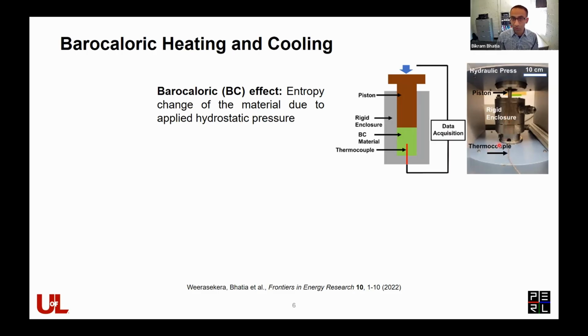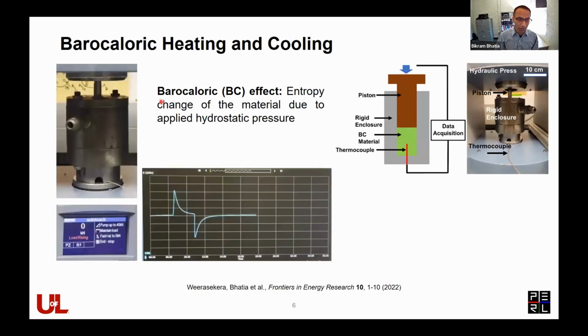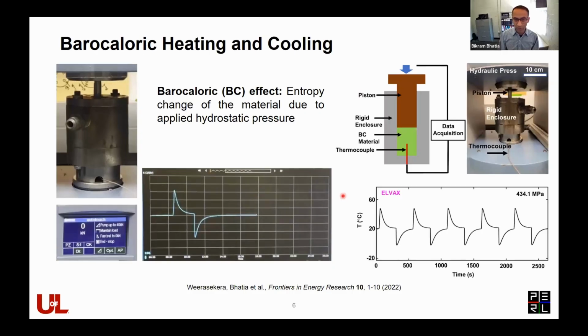And so you can characterize this barocaloric effect by applying hydrostatic pressure. So we do so in our lab using this stress rig that is shown here, which is essentially a piston cylinder system. You fill it up with a barocaloric material. You have a thermocouple embedded in it, and we measure the temperature as we apply pressure. And so as you do that, the temperature of the material rises. You let it equilibrate, come to room temperature. And then when you release the pressure, you see that the temperature drops drastically, and then again, it sort of equilibrates with the environment. So you can do this material testing for a wide variety of materials.